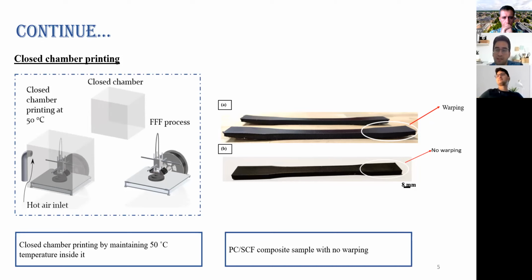What we are doing is regulating the surroundings of the 3D printing. We did two experiments, one without controlling the surrounding temperature of the 3D printer, and one by controlling the surrounding temperature. As you can see in figures A and B, A is without controlling, B is with controlling. In figure B, you are not seeing any warping. Here we did the 3D printing of composite parts in a closed chamber by maintaining 50 degrees Celsius around it. That totally eliminates the warping of the high temperature polymers, and the mechanical performance also improves. So this is the step we used for high temperature polymers if you want to use those polymers in the automobile sector. Okay.